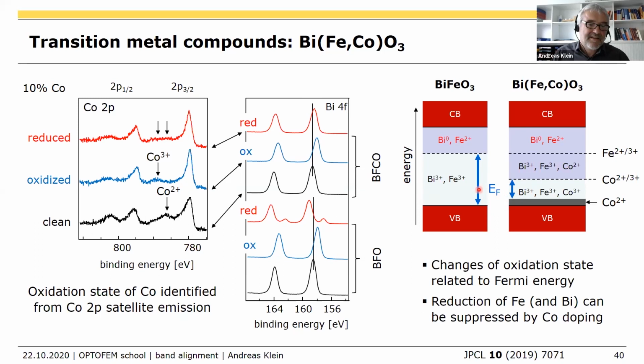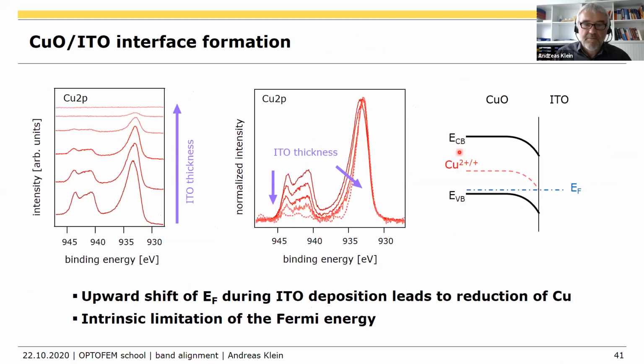Okay, so that's really a nice example where we can combine chemical changes and electronic changes. And our interpretation of these data is that the reduction of the pure bismuth ferrite is caused by the fact that we get metallic bismuth and iron because we raise the Fermi energy too much. Okay, similar things happen at copper oxide when we deposit ITO.